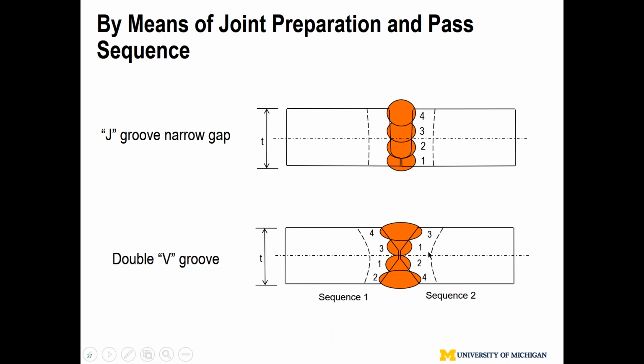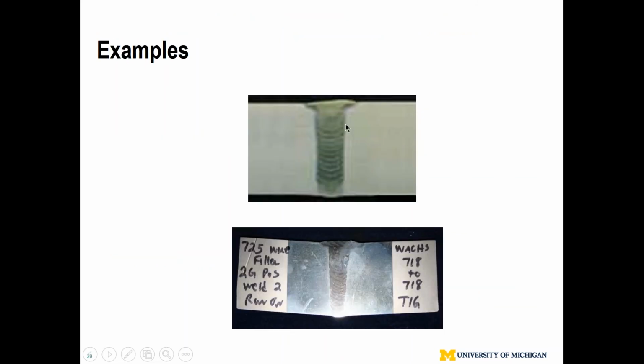and then you have stability. So again, when I say they don't have to be perpendicular, they can be any angle; the only thing we require, like a double V, is symmetry with respect to the neutral axis of the mid thickness. So that means double V works better, but you need clamping. If I use clamping, you don't need to follow the sequence 1, 2, 3, 4. That's not necessary. I can do 1, 2, 3, 4, or any other scenario as long as I have a clamping system to keep things in place.